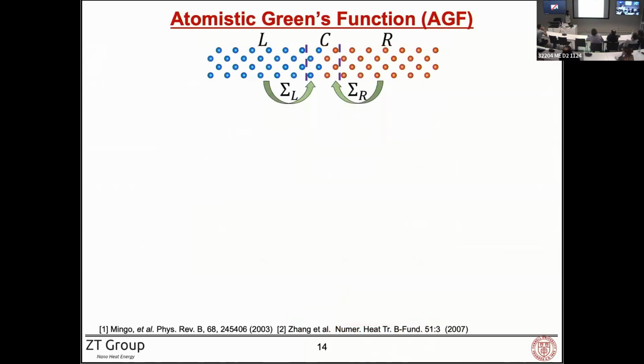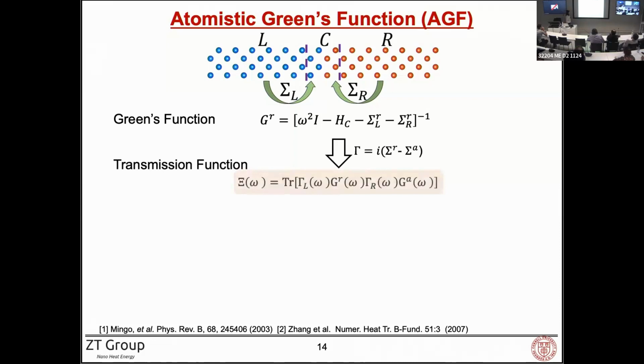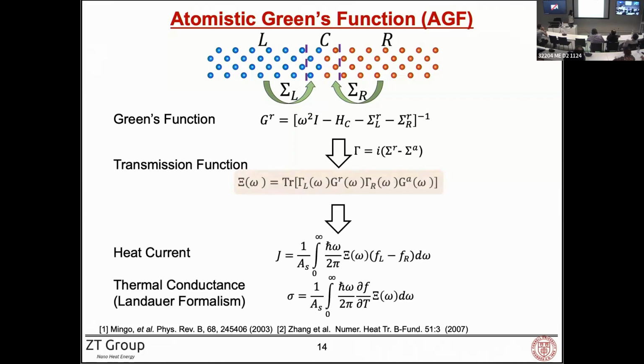A very brief summary of the atomistic Green's function method. Typically, when you have a system that is infinitely large, you partition it into three parts. You put the physical interface in the center region. The retarded Green's function describes the dynamics of phonons in the center region by taking into account the effects of the left and right leads through the self-energy terms, sigma L and sigma R. With that, we can write out the transmission function and then calculate the heat current and the thermal conductance using Landauer's formalism. A very detailed derivation can be found in Mingo's paper and Tim Fisher's paper. Those two papers I read many times.